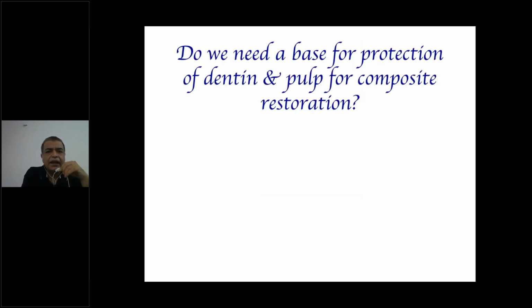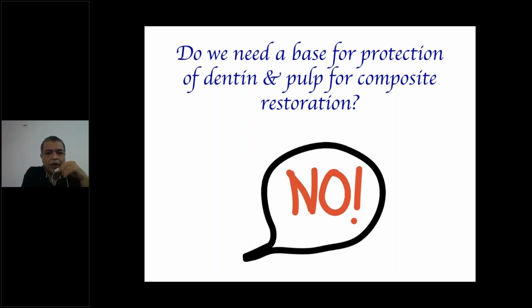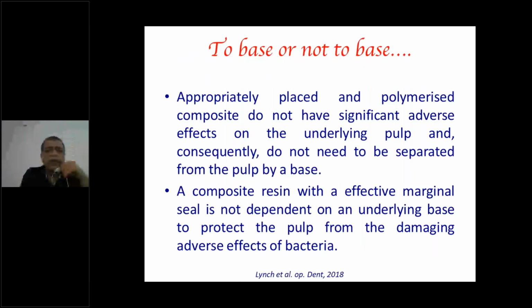When you come to clinical consideration, there's one question which is always in the mind of many practitioners. Do we need a base for protection of dentine and pulp for composite restoration? My take on that is absolutely not. And this no is not based on my personal perception, but on the studies which have been done. Studies have shown that a composite resin which has an effective marginal seal is not dependent on any underlying base to protect the pulp from the damaging effect of bacteria, and a polymerized resin does not have any adverse effect on pulp, so you need not separate it from pulp by a base.